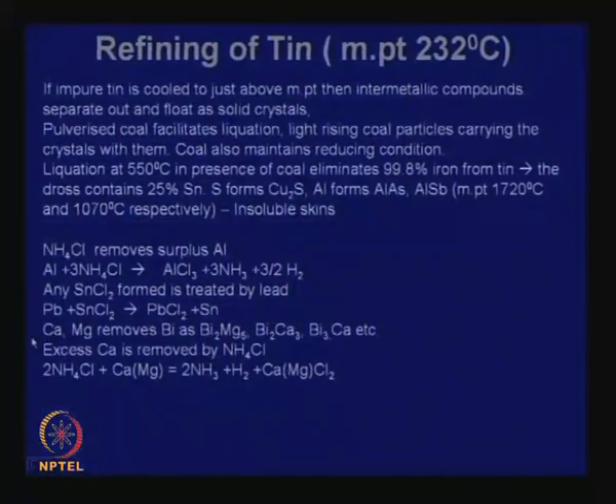I will give you a flow sheet, but you must understand how the flow sheet has evolved. One will add calcium and magnesium to impure tin to remove bismuth as a bismuth-magnesium compound and a bismuth-calcium compound. There are two of them, and since you are adding excess calcium, that excess calcium will be removed again by adding ammonium chloride. So, the impure tin has to undergo all these steps so that we can finally produce pure tin. These are various steps, and there is a flow sheet that should make it a bit clearer.